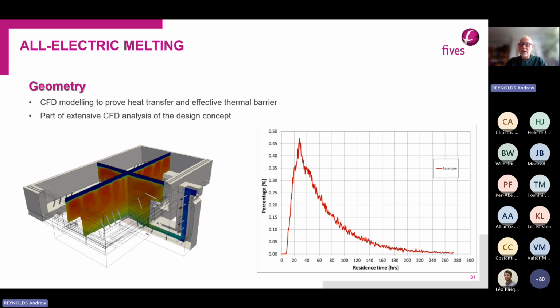the residence time of the melt inside the furnace, which is a key part in determining the quality of the glass coming out of the system. And in fact, we determined that we could move safely from the standard hexagonal design that's used on the smaller furnaces to a rectangular design without endangering the quality of the product. The rectangular design was also considered to be a good option because it's a better stepping stone to even bigger furnaces, which might be considered in the future.